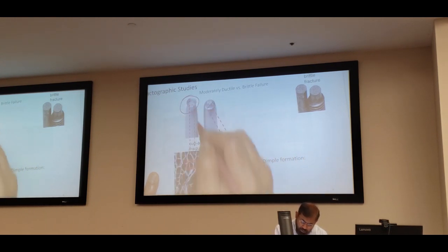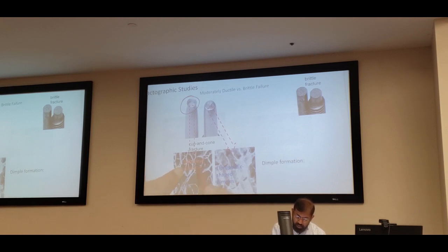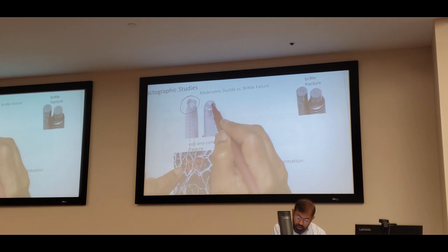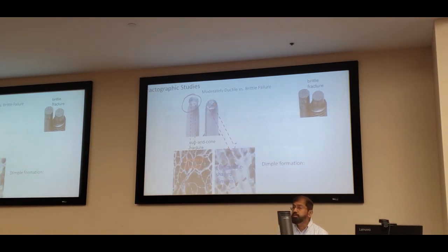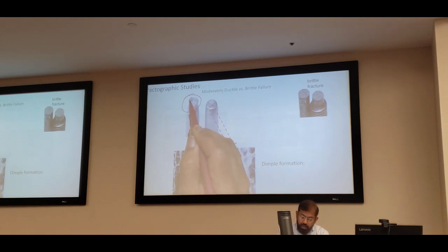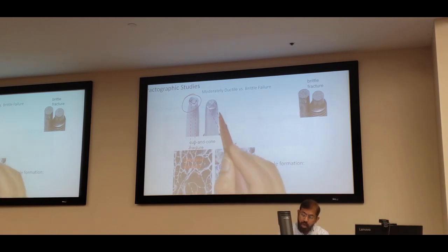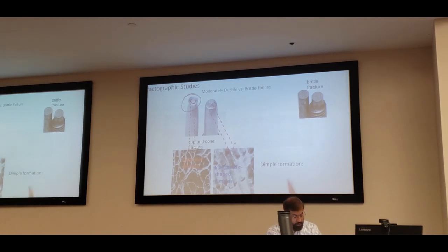So the cup region, shown here, is where you can see the spherical dimples, and where the cone lips are, at the lips, you can see the elongated C-shaped dimples. So on the cup side you can see spherical dimples, whereas on the other side you can see elongated C-shaped dimples. So this is how you can analyze your failure. This dimple formation is a characteristic of uniaxial tensile failure.